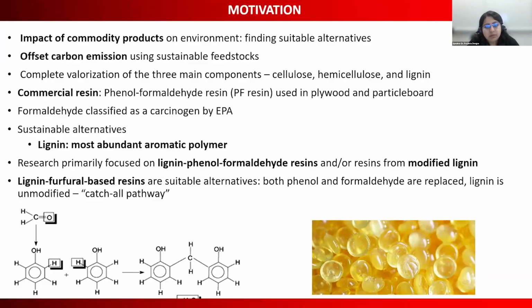However, the work that I did as a part of my thesis was to use lignin unmodified, as is, and then cross-link it with furfural to make your lignin furfural resins, which is also referred to as the catch-all pathway. So you're not purifying or fractionating or modifying lignin in any way. You're just taking the lignin as is and producing materials from it.